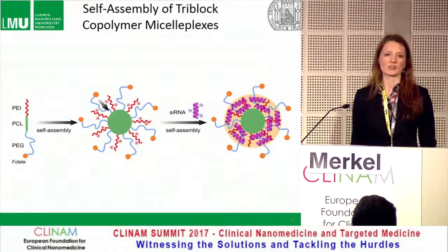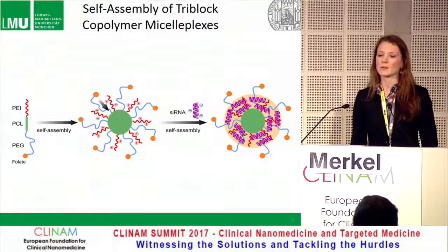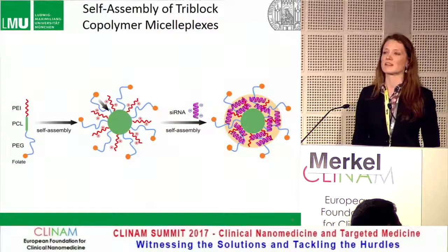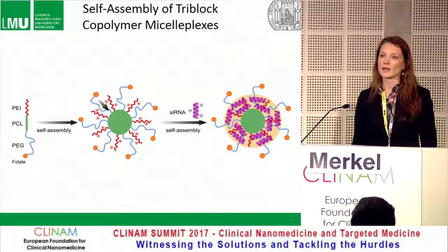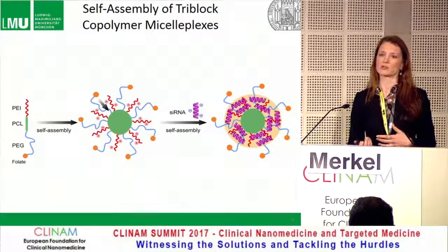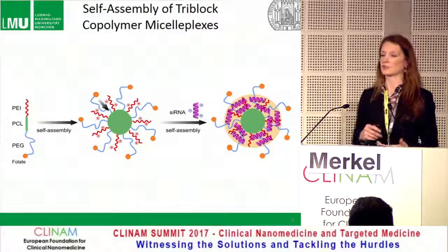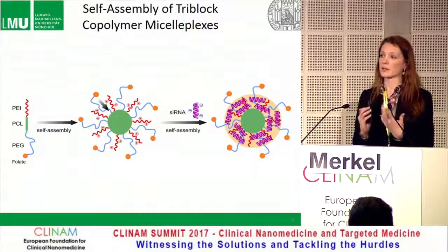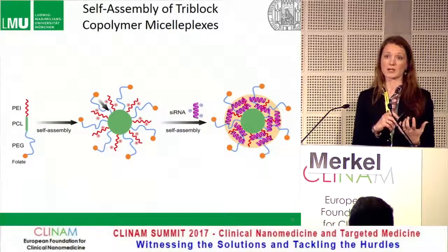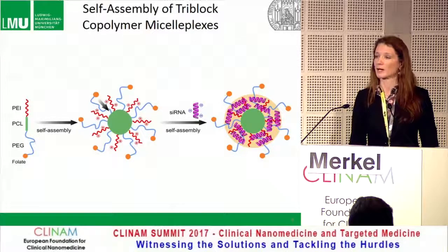PEI is certainly not a very translational polymer, so we're currently working on replacing the positively charged PEI part with more biodegradable polyamines. This type of tri-block copolymer has been extensively researched in terms of in vivo circulation times — those micelles circulate for a long time and have advantages because of their hydrophobic core. For RNA, the amphiphilic structure is very helpful as it aids not only in delivering particles across the cell membrane but also with endosomal release, since these particles don't suffer the endosomal entrapment often seen with polymeric nanoparticles.